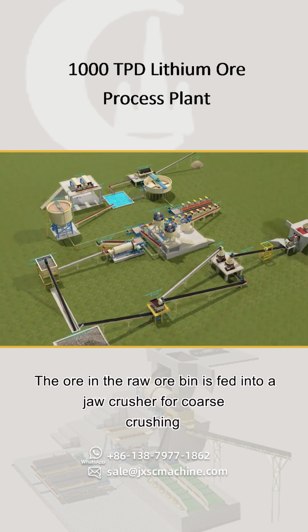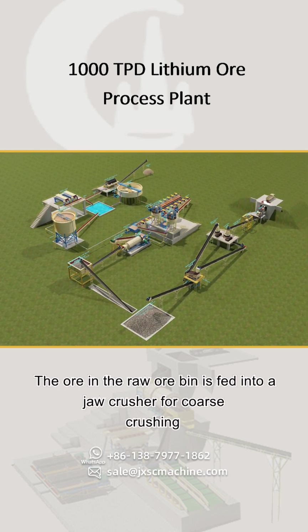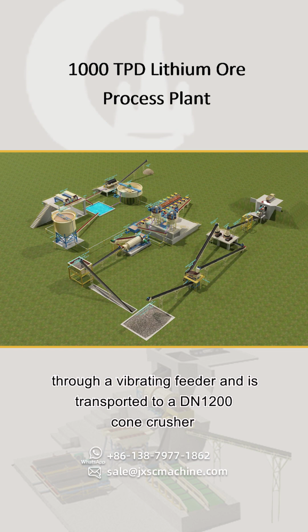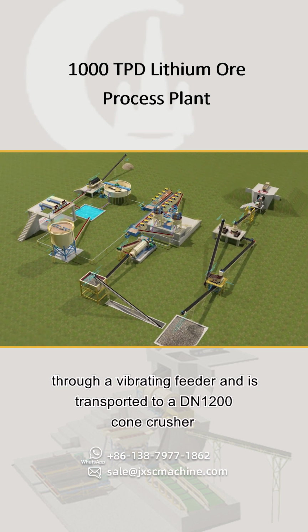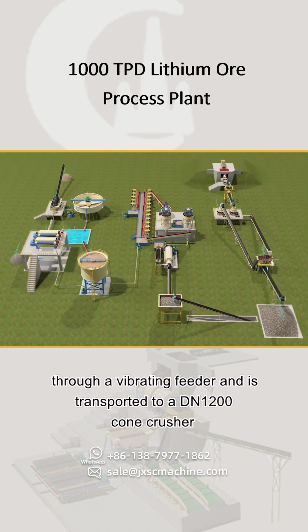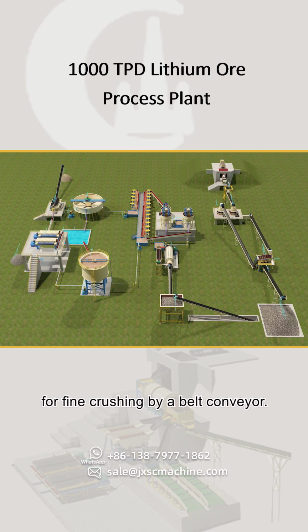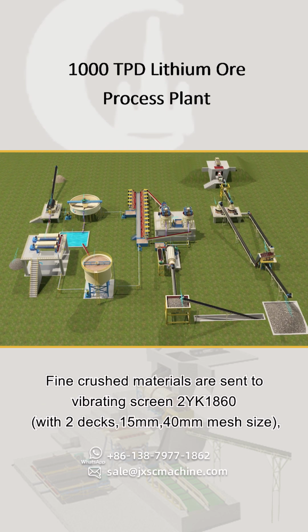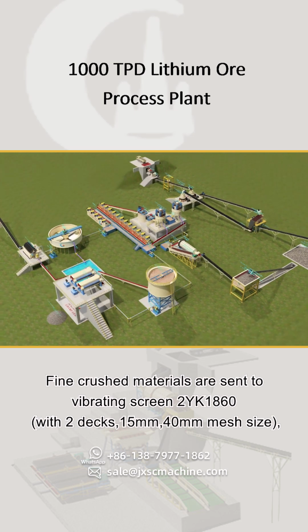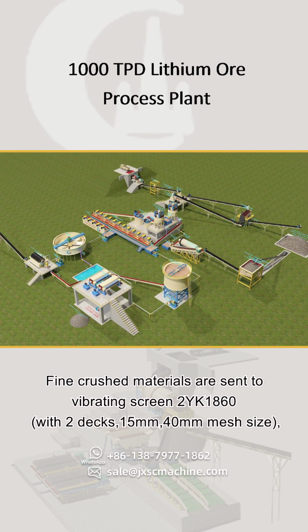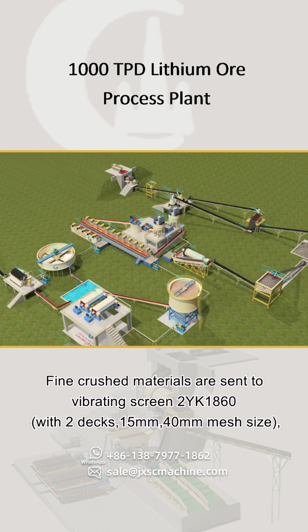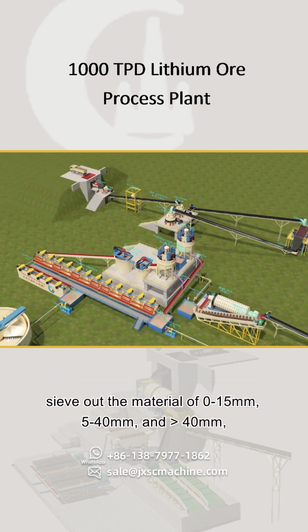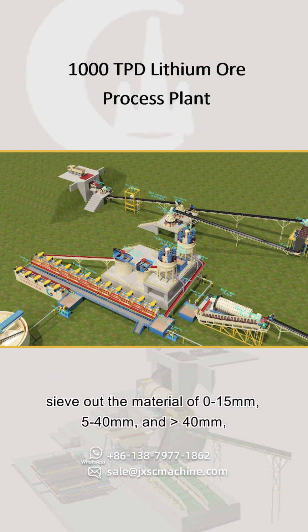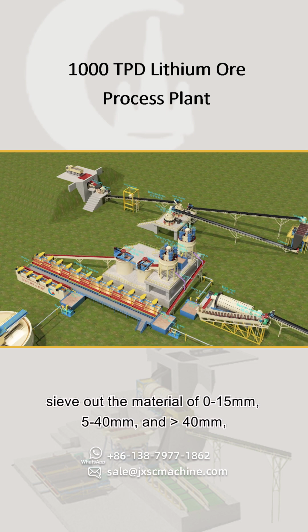The ore in the raw ore bin is fed into a jaw crusher for coarse crushing through a vibrating feeder and is transported to a DN 1200 cone crusher for fine crushing by a belt conveyor. Fine crushed materials are sent to vibrating screen 2YK1860, with 2 decks, 15 mm, 40 mm mesh size, to sieve out the material of 0 to 15 mm, 15 to 40 mm, and more than 40 mm.